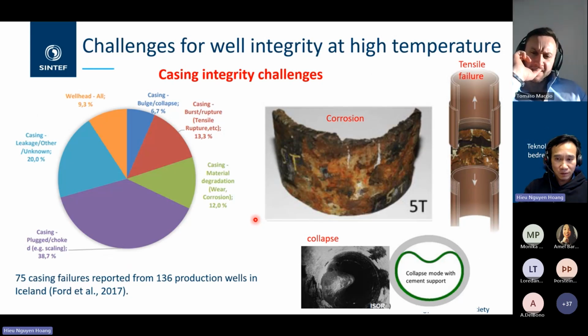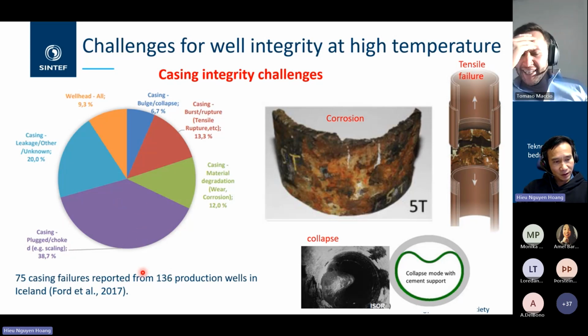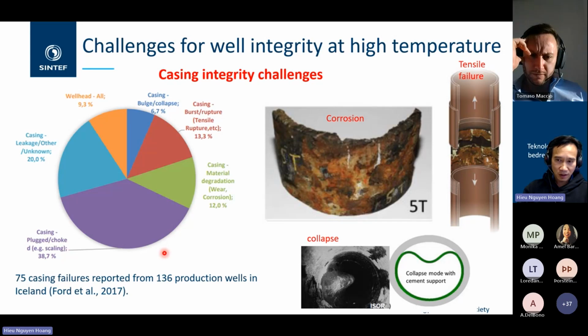And a lot of data from previous projects have shown the severity of the casing integrity challenge. For instance, this figure shows an example of an Icelandic case. More than 50% of investigated production wells, as you see here, are reported with casing failure in one way or another. You may see casing corrosion, tension stress failure, casing collapse. And it shows the need for a more robust solution to withstand these harsh thermal conditions in these wells, not only for super hot application, but also for conventional high temperature application that we see here in this report.